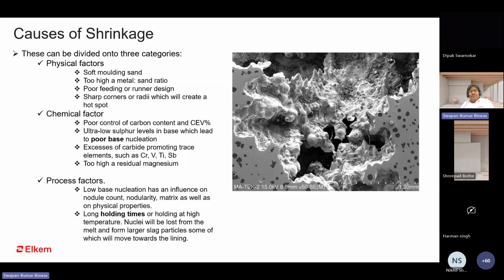So on one side you are protected, as there will be no compacted graphite due to this high residual magnesium, but on the other side you will face other metallurgical problems. So optimum residual magnesium is the most important for ductile iron. Normally 0.035 to 0.045 is the ideal range of residual magnesium. But it will vary depending on the casting size and thickness. For bigger sizes, maybe slightly higher residual magnesium is needed. But in other automobile castings, mostly this range will be the most preferable range.